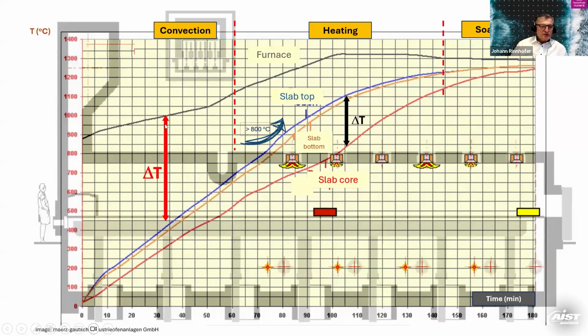So high temperature differences are very good usually for heat transfer, because the transferred heat is a function of the temperature difference from the furnace temperature to the surface temperature of the slab. So we're talking about the surface temperature only, not the average temperature of the stock. The surface temperature is shown here as the slab top temperature. This is the blue line here. The slab bottom temperature is the orange line here, and the slab core temperature is the red line.